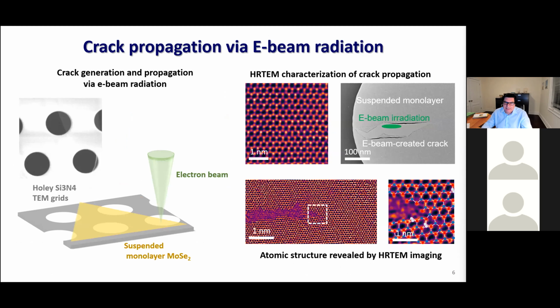Let me start by sharing some details of what type of measurements you can do in this first approach, where you transfer the flake onto a TEM grid, and then use the electron beam irradiation. Typically, the electron beam is operated at 200 kiloelectron volts. The kinetic energy that the electron carries can produce vacancies, and if you increase the dose, you will induce a crack. Here is an example of a crack induced in the monolayer in the suspended specimen.